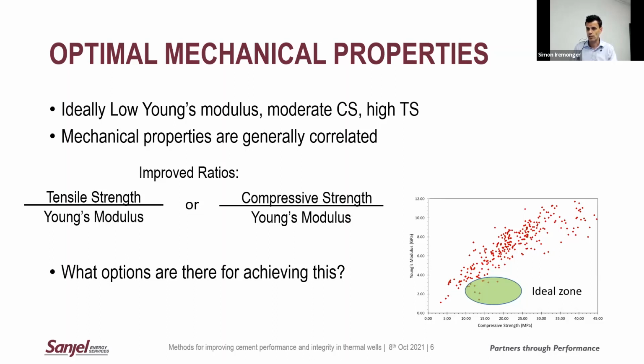And so, it's good not just to focus on an individual property, say, hey, we've got a nice low Young's modulus, but look at all those parts working together. One way you can do that is to look at the ratios of your tensile strength to your Young's modulus, or your compressive to your Young's modulus, to show that you're getting a disproportionate enhancement of one property without sacrificing the other too much. If you look at the range on the scatter plot, an ideal range, as I said, would be a nice low Young's modulus and moderate compressive strengths. So what options are there for achieving this?